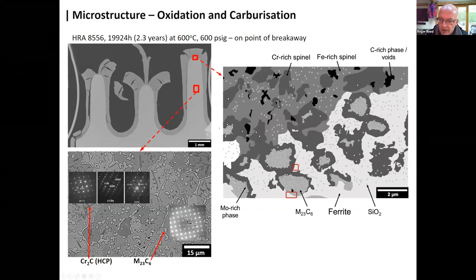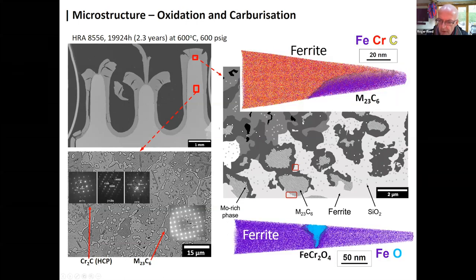The carbides are being attacked by a mixture of iron-rich and chromium-rich spinels, and we have also found evidence of porosity and even graphite at this interface in these materials. And a lot of lift-outs using modern techniques based upon atom probe tomography to confirm the chemistry and the microstructure of these phases. Of course, none of these things were possible when I started my PhD with Harry, but more and more, of course, these methods are becoming more routine and standard.